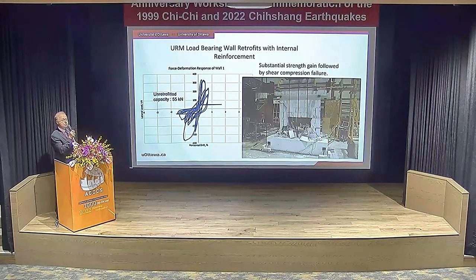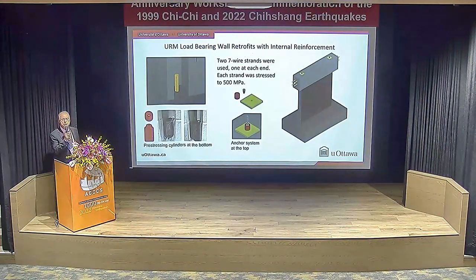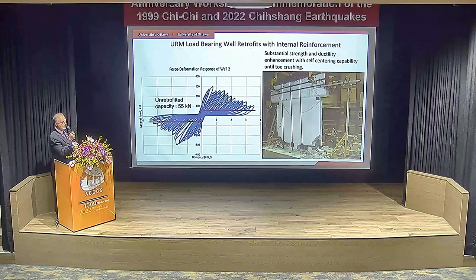So there was a strength enhancement. Obviously, when you retrofit URM walls, you have to perhaps use elastic concepts like expect elastic behavior. It would then be simply strength enhancement rather than ductility enhancement. So the next specimen was reserved for pre-stressing URM walls, and we did pre-stress them. As you can see, we once again used cylinders and anchored them to the foundation and applied pre-stressing. And we pre-stressed up to 500 MPa, and these strands had 1860 MPa capacity.